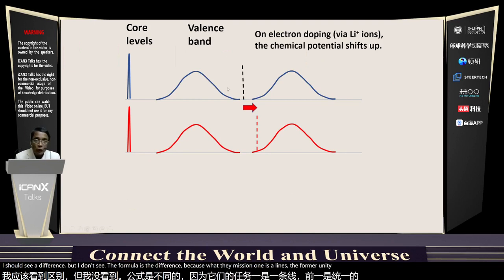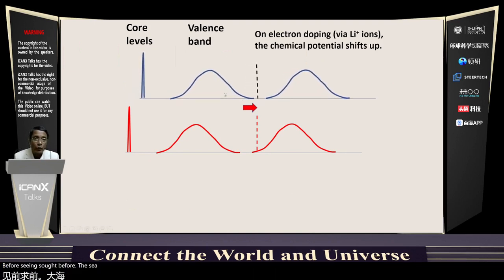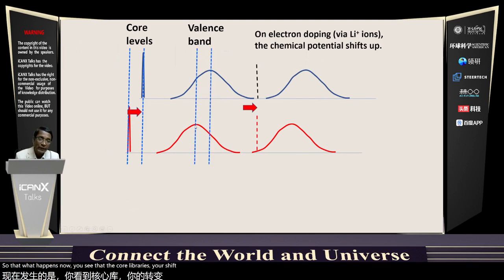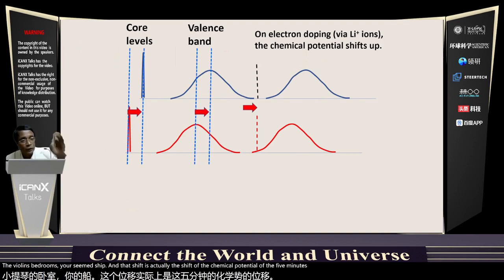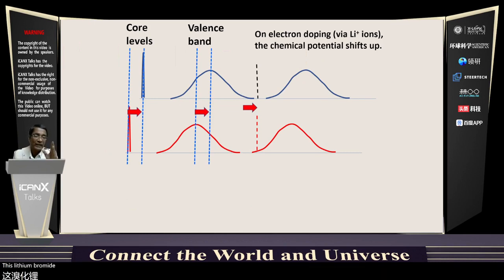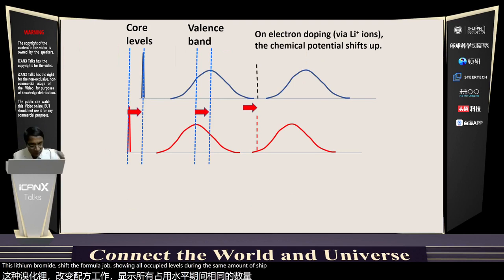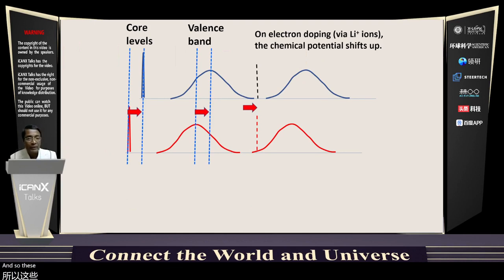Before recording, I align the Fermi energy. So what happens now, you see that the core level will show a shift, the valence band will show a shift, and that shift is actually the shift of the chemical potential or the Fermi energy because it got doped by lithium. This lithium doping shifts the Fermi energy up, showing all occupied levels showing the same amount of shift, and so this doping makes the system appear metallic.